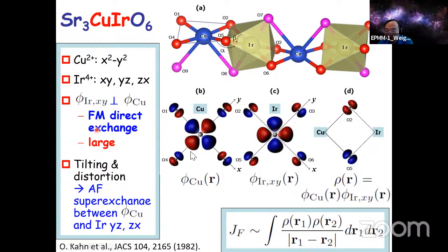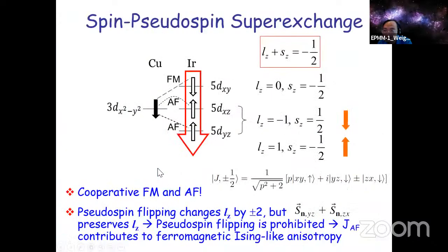So now in the normal 3D and 5D materials, there is competition between the ferromagnetic and antiferromagnetic interactions. So whether the system is ferromagnetic or antiferromagnetic depends on their relative strengths. But here, why is the system ferromagnetic, and also why does it display strong ferromagnetic anisotropy? It is because here the iridium pseudospin has the internal structure. See, the real spin on the xy orbital is opposite to the real spin on the other 2 orbitals. So you can see this one is ferromagnetic coupling, so they are perfect. And also this antiferromagnetic coupling is also perfect. So there's no competition. They are cooperative. So this generates a large ferromagnetic interaction in the system.